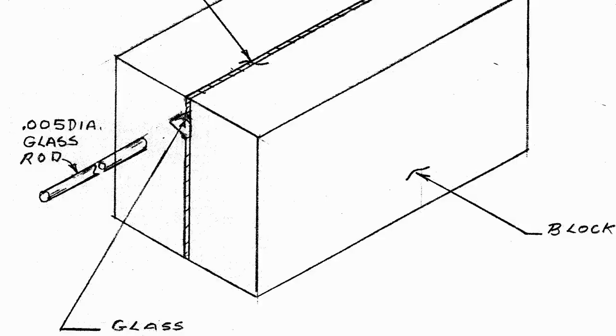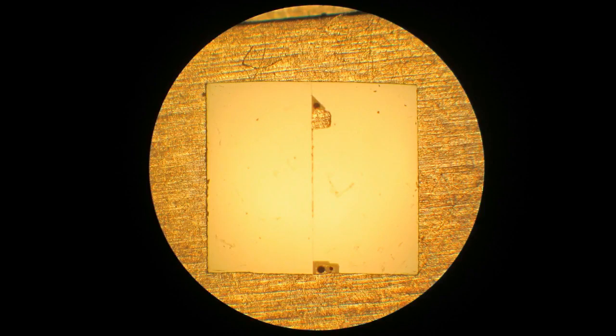So you would have the two pieces clamped there, separated with your shims, so you have a little crack between them. And in the winding window or above or below, you would situate your brazing rods, your glass rods, or if it was glass powder, you'd pack it into your window or your channel if you had a channel, which we had both. We had a back channel and a winding window that we packed with glass. And you put that in your oven and heat it up, and through the capillary action, the glass is sucked down into that void, that crack or that gap between the two pole pieces.